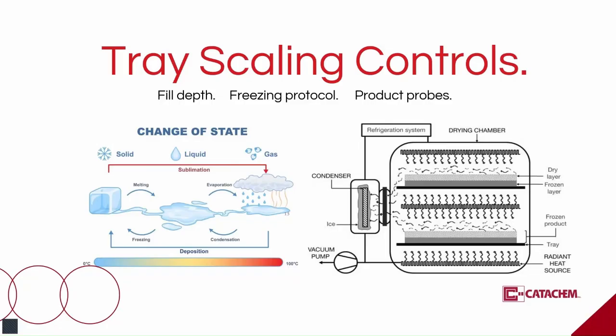Third, monitor product temperature, not only chamber conditions. You need probes in multiple locations, center, edge, potentially multiple depths depending on the format, to verify the product never drifts above collapse temperature. At Catachem, we operationalize this with test batches and temperature mapping in representative loads. It is a faster path to a robust recipe than guessing with time alone.